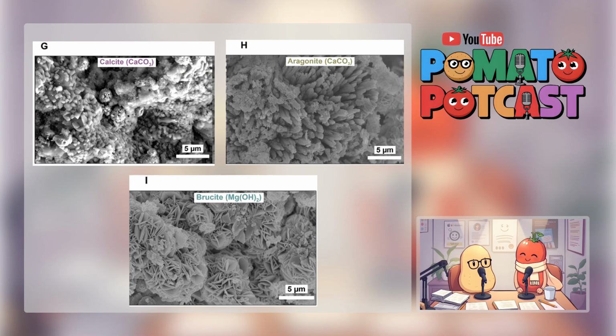As the aggregate grows, the effective current density seems to drop, which actually helps the aggregate stick better and continue growing stably. They even found the shape of the electrode you start with can influence the final shape of the aggregate. So you could maybe grow specific shapes. That's wild. What about the inside of these aggregates?